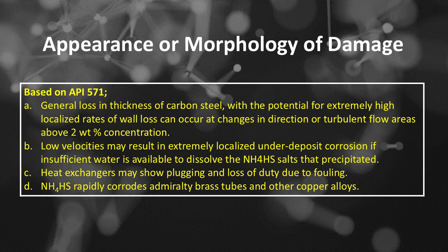Low velocities may result in extremely localized under-deposit corrosion if insufficient water is available to dissolve the NH4HS salts that precipitated. Number C: heat exchangers may show plugging and loss of duty due to fouling. Number D: NH4HS rapidly corrodes Admiralty brass tubes and other copper alloys.